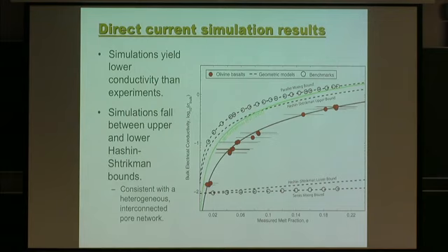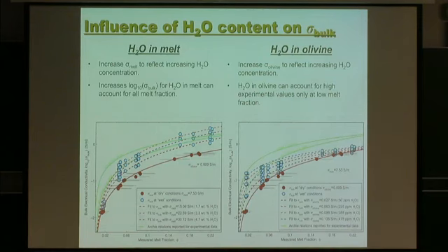So what we think might be happening is, first, what we take in our virtual experiment is that the olivine's conductivity and melt conductivity are completely dry conductivity, all right? And in the experiment, those are actual ones. So even if they are dry, they may be nominally dry. So we don't know how much water content is there.